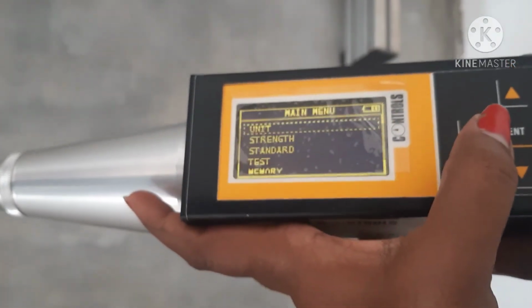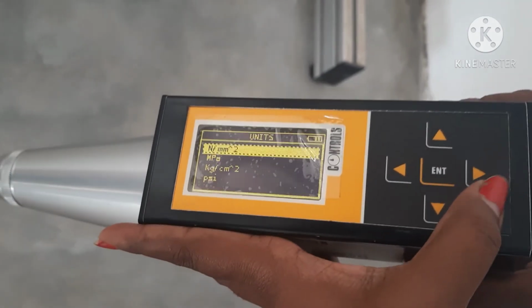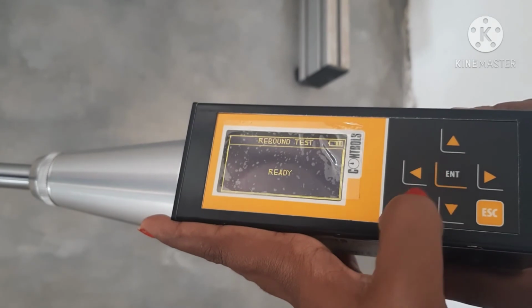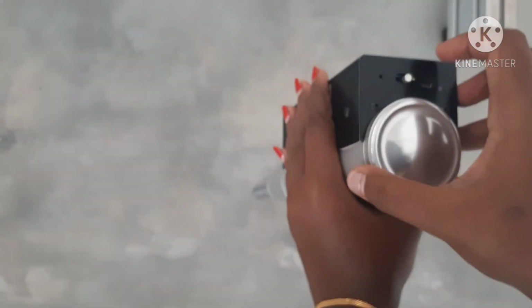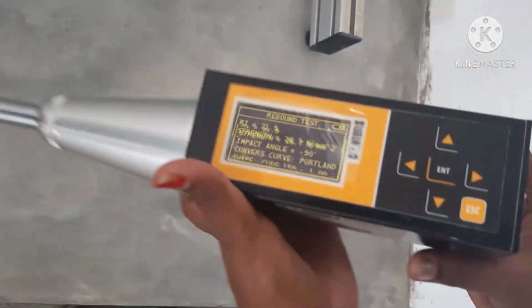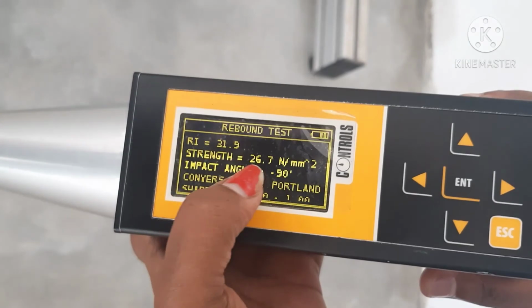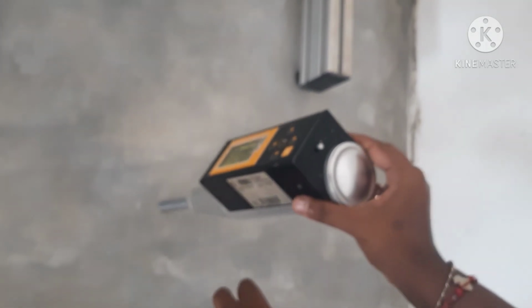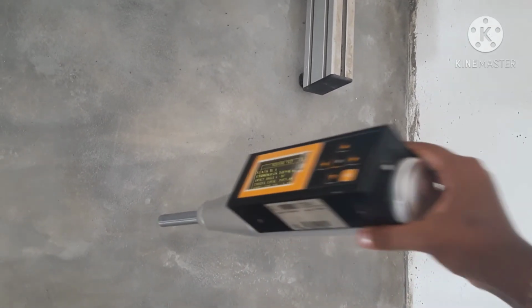We cannot come to a conclusion with only one hammer test, so we have to do it several times on the same point and take the average, and then we can state the compressive strength of the particular structural element. Similarly, we have to carry out the same procedure and find the compressive strength for a horizontal surface as well. Here also we have to follow the precaution. The surface should be clean. Now our rebound hammer test is done and we are able to see the test results. The rebound index is 31.9 and the compressive strength is 26.7 Newton per millimeter square. Likewise, we have to take several readings and find the average of those readings to get the compressive strength.